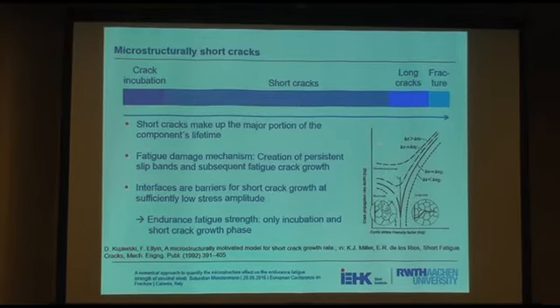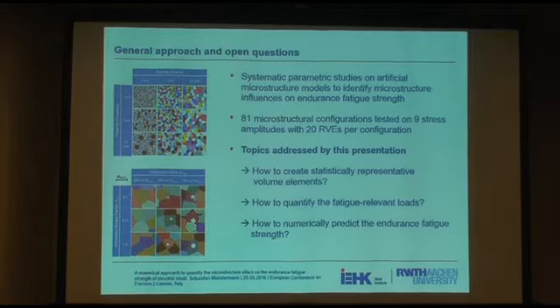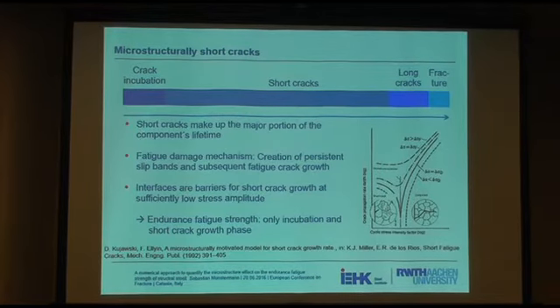So what we understand is that short cracks make up the major portion of the component's lifetime. And the fatigue damage mechanism in this phase for the short cracks is the creation of persistent slip bands, which govern mainly the incubation phase and also the short crack phase, and then the subsequent fatigue crack growth. And for short cracks and long cracks, there's a certain transition in cyclic growth mechanism. What's very important, especially for steels, is that interfaces are barriers for short cracks, at least if the applied stress amplitude is not sufficiently high. So it means that a short crack can grow, but if the stress amplitude is not sufficiently high, for a significant number of cycles it will not be able to pass this barrier and then run into the neighbor grains.